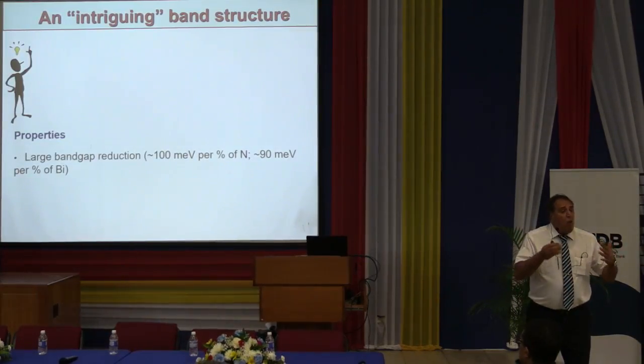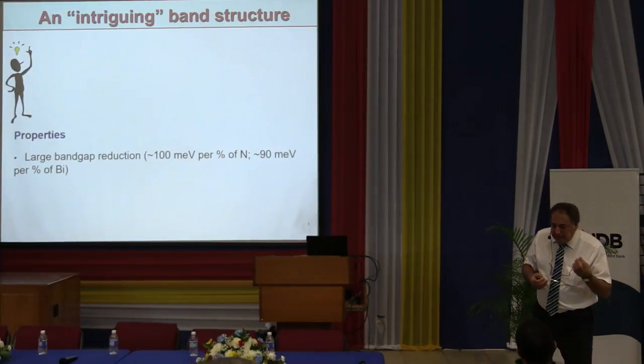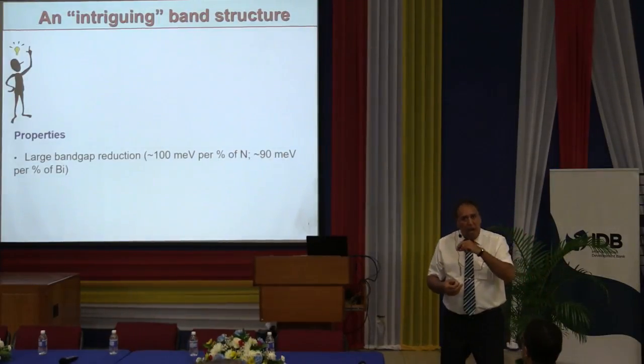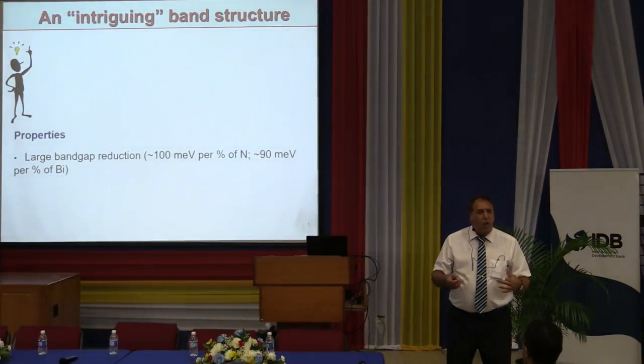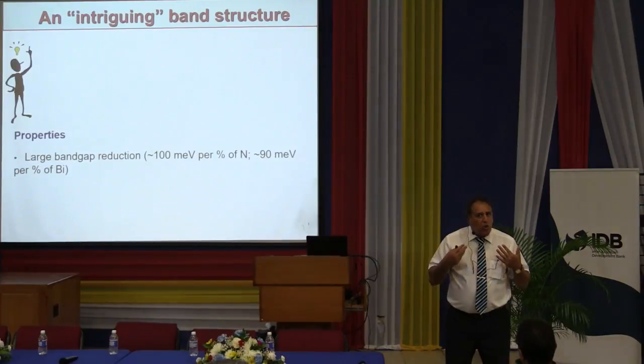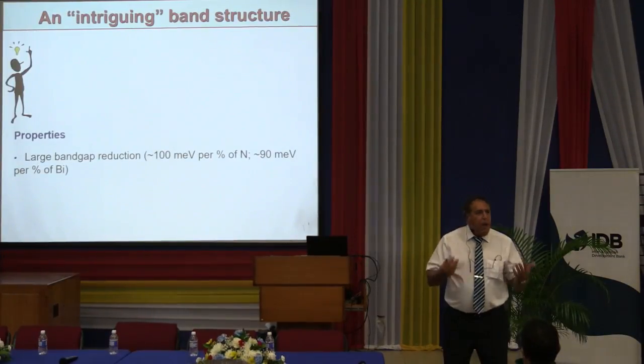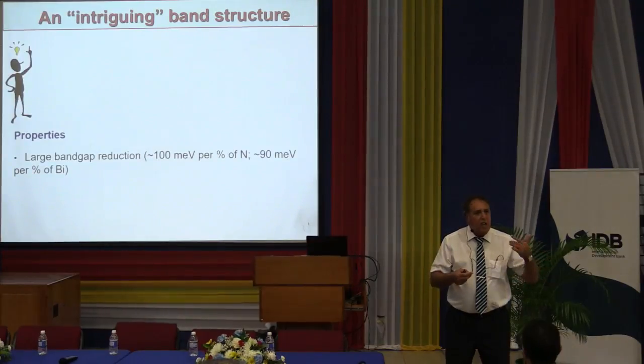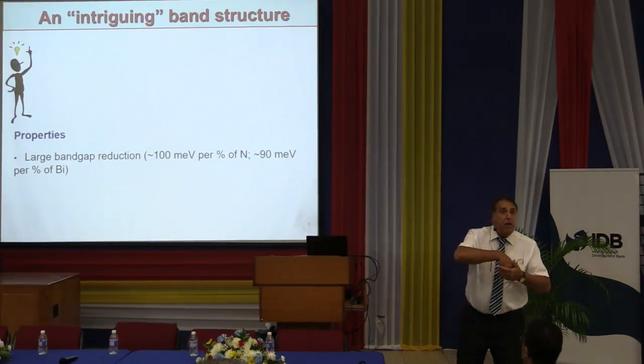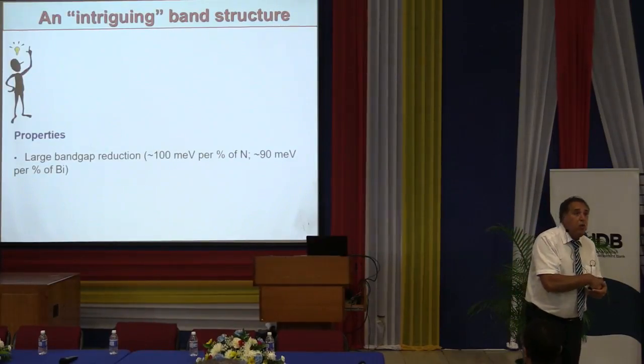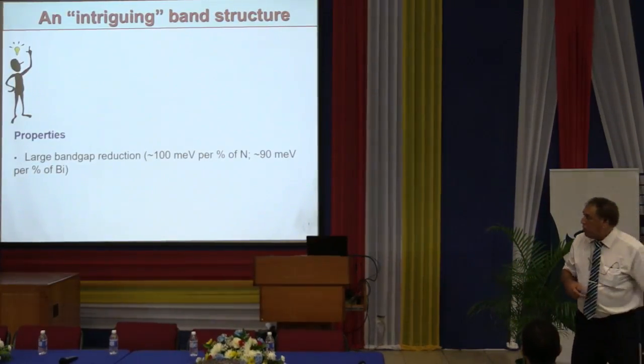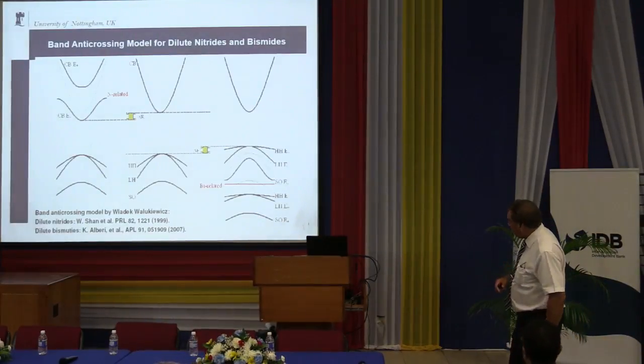Again, when people found this, including ourselves, the problem is, when you grow this material system, replacing arsenic by a smaller atom or bigger atom, the optical and the electrical properties are very different than the gallium arsenide. Although the size is the same, the properties are very different, and they grow in a different way. So there was a lot of hard work to really optimize those properties, both electronic and optical, in order to integrate them into the 3 junction cell to have something useful and increase the efficiency of the solar cells.